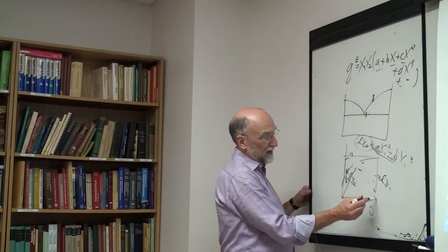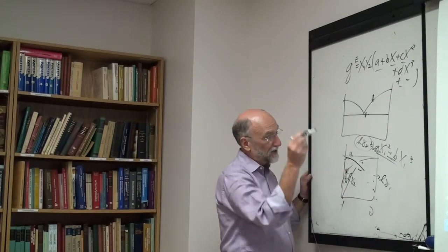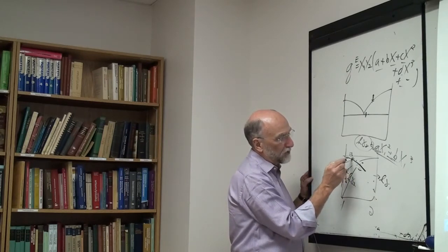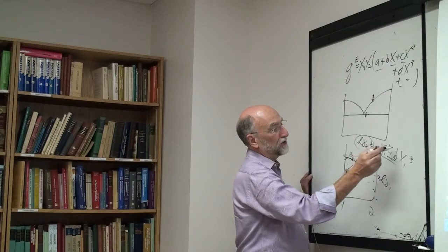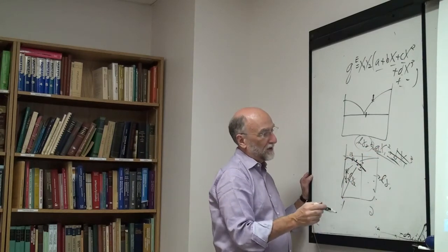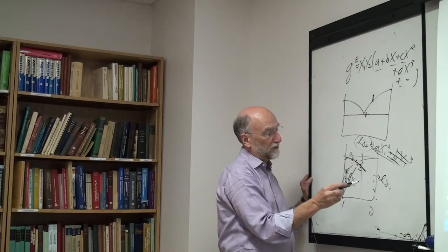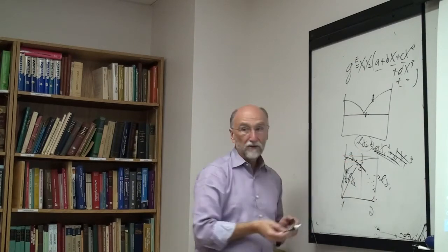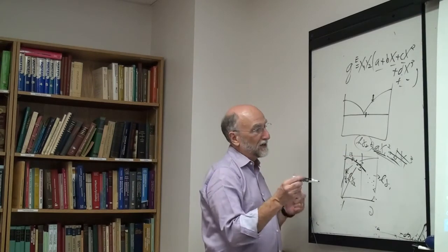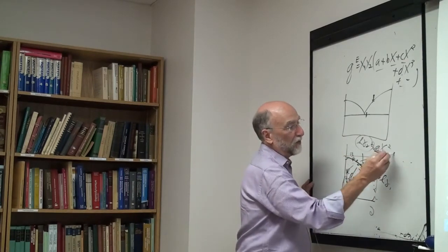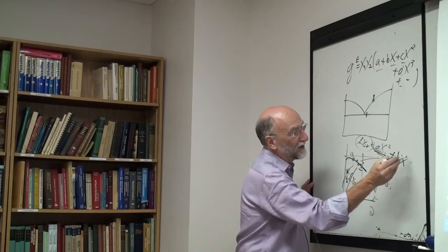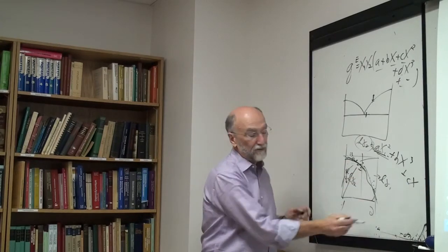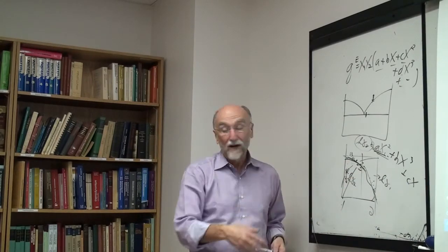Also, say you want to extrapolate. You measured the zinc cadmium. You've measured log gamma zinc over this region, and it fits pretty close to, say, a 1 coefficient equation over 50%. Well, that indicates the system probably isn't too far from regular behavior, so you can probably extrapolate it and get not too bad an integration of your Gibbs-Duhem equation. But then you get a little bit silly and say, well, let's add a couple more terms just to get the fit perfectly over here. Okay, and then you get a perfect fit over here, but when you extrapolate it, the more terms you add, the worse your extrapolation is going to be.